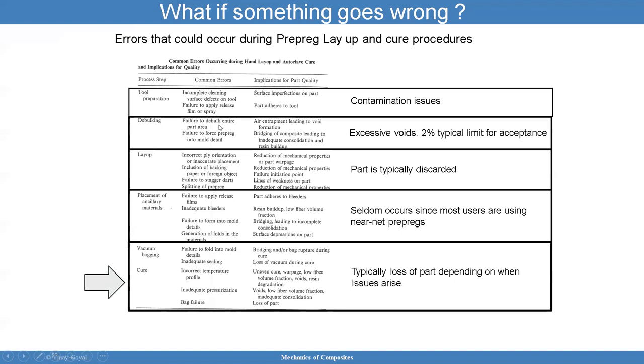Debulking: failure to debulk the entire part area can lead to air entrapment leading to void formation. Failure to force the prepreg into the mold detail means that you may have inadequate consolidation and resin buildup. We want to really limit voids. We want to limit voids to perhaps 1% as our goal, but we don't want it to be greater than 2%. It's the typical limit used in the aerospace industry.